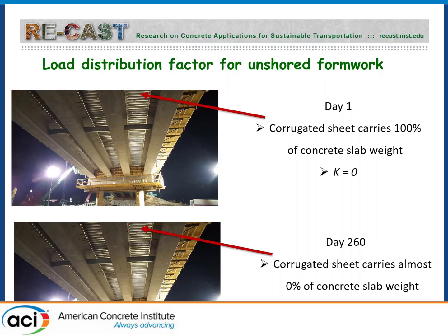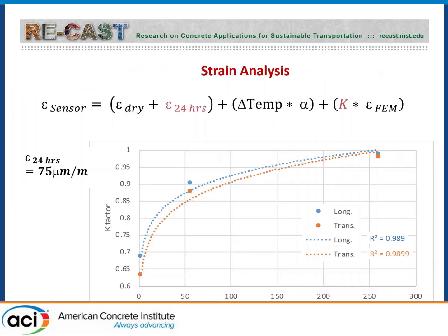But later we found out that if you go up to about 260 days, then all the load is really carried by the pre-stressed girders. So there was some analysis done from the finite element analysis and the sensors at different levels at different ages, knowing the temperature variations, knowing the shrinkage. We calculated the autogenous shrinkage to be 75 microstrain, which is very reasonable. It confirms the results we had in the lab when we developed mixes like that. We also were able to determine the K factor.